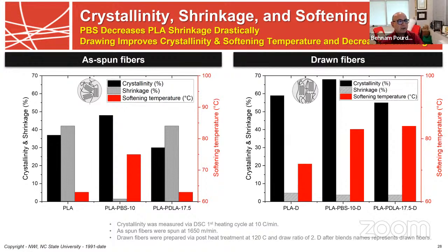When you look at fully drawn fibers, the story changes. So if you had a fully drawn fiber, the PLA by itself is now almost 60% crystalline. Its shrinkage is about 5%, and its heat deflection temperature is still about 68, 70 degrees.